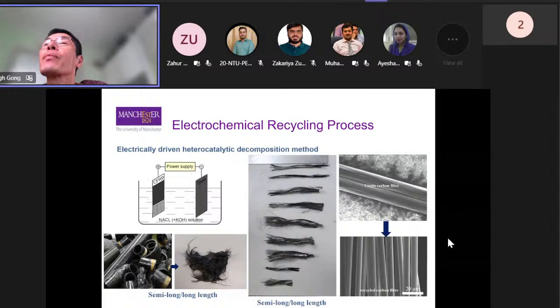Anyway, so as I said, we had a collaboration with Shenzhen University, because they developed a new process of recycling carbon composites. And one of our staff members was part of that project. It's essentially a chemical process, but assisted by electrical current. So what they found is they can use this to recycle carbon fibers from composites at room temperature. And there are no harmful chemicals generated, and also they can preserve the carbon fiber performance after recycling. In other words, if you test the individual recycled fiber, its performance is comparable to virgin fibers.